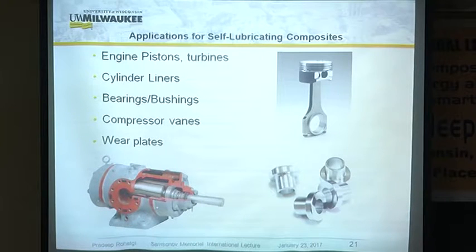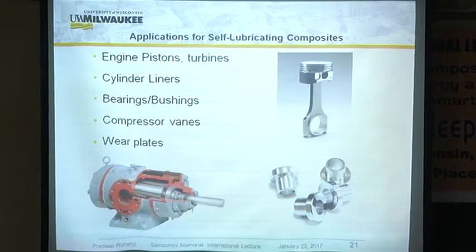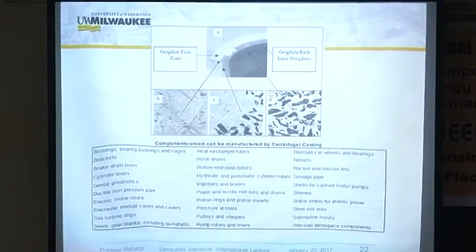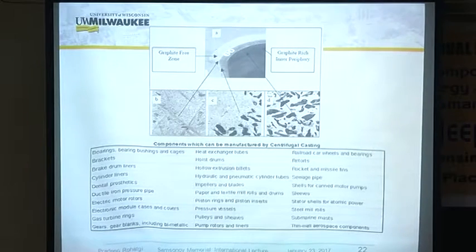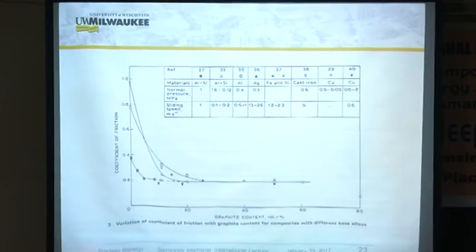Let me talk to you a little bit about the potential applications. I did talk about putting graphite in aluminum, and it makes aluminum self-lubricating. The friction coefficient goes down, the wear rate goes down, and that is why it is a very desirable material for pistons and liners and so on. So in a single step centrifugal casting process where the graphite was dispersed non-uniformly in a melt, when I centrifuge, they bring the graphite to the inner periphery, and that's where you need it for bearings and for cylinder liners. A single step process to produce a functionally gradient composite which can be manufactured. This was funded by Ford, and by introducing graphite, the coefficient of friction comes down from 0.8 to 0.2. So a lot of energy in Indian cars could be reduced if you use the self-lubricating lightweight aluminum graphite cylinder liners.